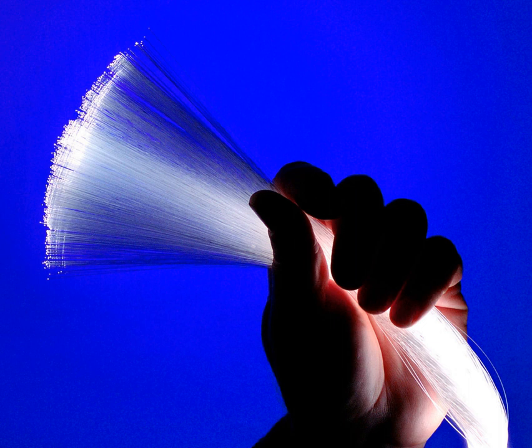The waveguide analysis shows that the light energy in the fiber is not completely confined in the core. Instead, especially in single-mode fibers, a significant fraction of the energy in the bound mode travels in the cladding as an evanescent wave. The most common type of single-mode fiber has a core diameter of 8 to 10 micrometers and is designed for use in the near-infrared. The mode structure depends on the wavelength of the light used, so that this fiber actually supports a small number of additional modes at visible wavelengths. Multi-mode fiber, by comparison, is manufactured with core diameters as small as 50 micrometers and as large as hundreds of micrometers. The normalized frequency V for this fiber should be less than the first zero of the Bessel function J0.